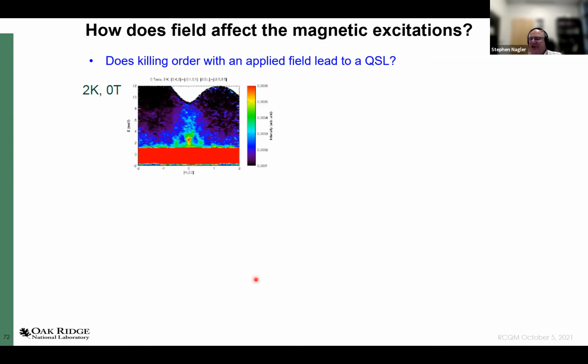And what I maintain is that we have something similar in spirit to what you see in the quasi 1D chains, which is when it's ordered, you see spin waves plus some continuum that could be coming from fractional excitations. And when it's disordered, you see only the fractional excitations.